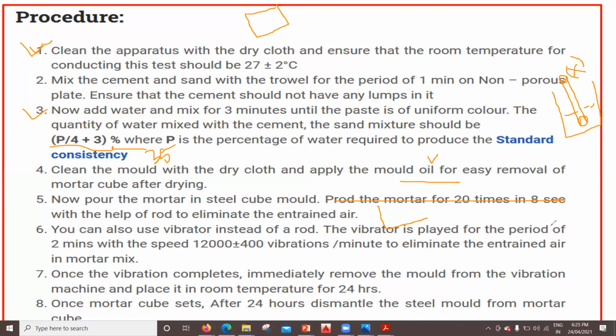The vibrator is played for the period of 2 minutes with a speed of 12,000 plus or minus 400 vibrations per minute to eliminate the entrained air in the mortar mix. So what is this vibrator? We'll be having a big shaking vibrator. Let me do it here. So let us say this is a table what we have, and we are going to keep the mold over that. So there is a vibration in this table. As a result of that, if there are any voids in this cement mold, they will get filled due to the vibration. So this is called a vibrator. So if you want, you can use a vibrator. If not, you can make use of this tamping rod.